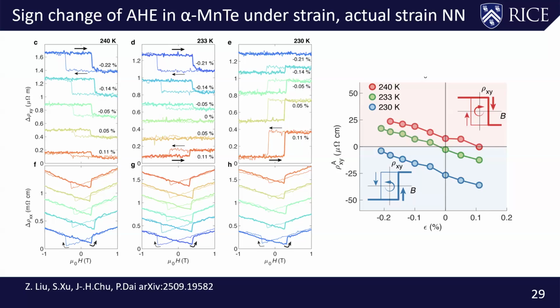And then at the same temperature, as you gradually apply a uniaxial strain from negative, which is compressive, to positive, it actually changes sign, becoming looping around the other direction. So this is actually very strange. I mean, anomalous Hall effect changes sign in a regular system as a function of temperature. That's not really surprising, because for any multi-band system, you can have electron and hole concentrations that can be different as a function of temperature. Yet, as a function of uniaxial strain, it changes sign. Not too many systems behave like that. I'll show a system that does behave like that later, but I'll argue that the microscopics are quite different.